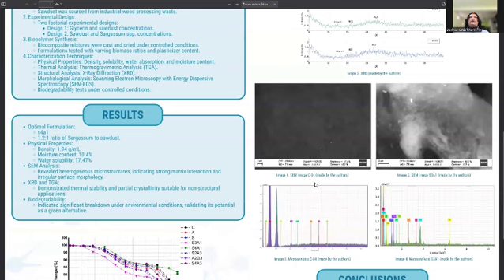For the results, we found that the formulation labeled S4A1, with a sargassum to sawdust ratio of 2:1, demonstrated the best overall performance. Its physical properties were a density of 1.94 grams per milliliter, which indicates a compact structure. The moisture content was 10.4%, reflecting moderate water retention. The water solubility was 17.47%, offering a balance between durability and biodegradability.